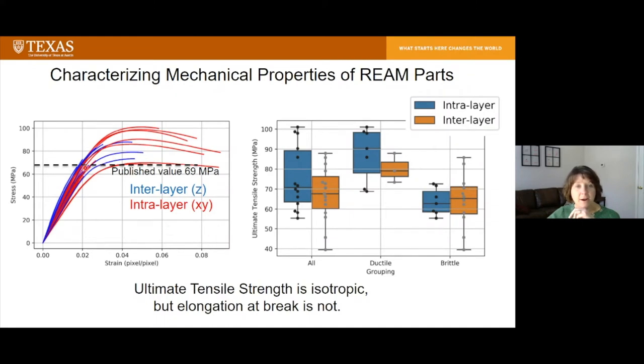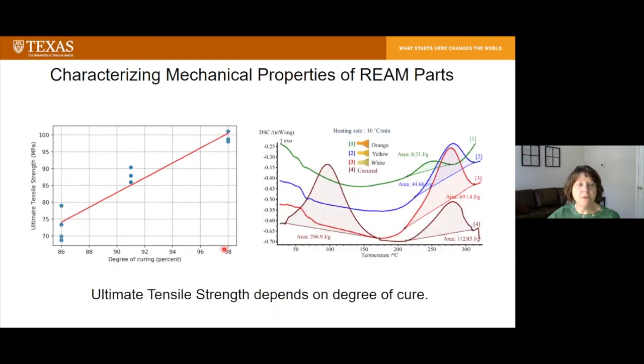The parts that are interlayer, or Z parts, tend to be a little bit more brittle than the parts that are tested within the layer. That could be due to a lack of fusion across the layers. But we do see polymer cross-linking across the layers, which is what accounts for that really nice strength across the layers as well as within. The other thing we're seeing is that the ultimate strength of the parts, you may have noticed some variability on the previous slide, and most of that variability actually is explained by the degree of curing of the parts.